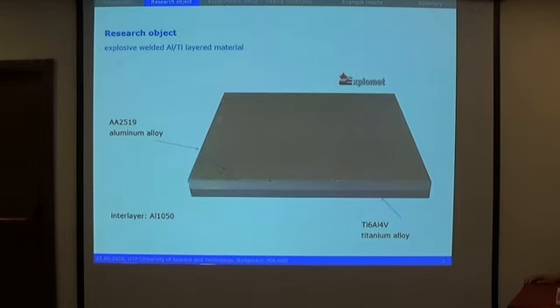Our material is a composition of two alloys. The first one is a titanium alloy, here's the description, and an aluminium alloy. The materials are mainly used for the aviation industry, for covering, for example, airplanes. And additionally, an interlayer was used. It was aluminium alloy Al1050. This material was used for improving the process of explosive welding. Of course, such technology requires a lot of heat treatment before the joining and after the joining, but it was described in another publication.